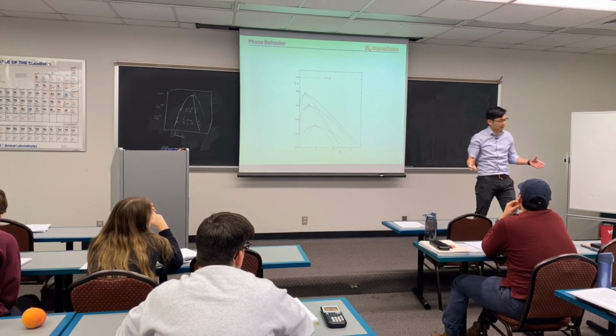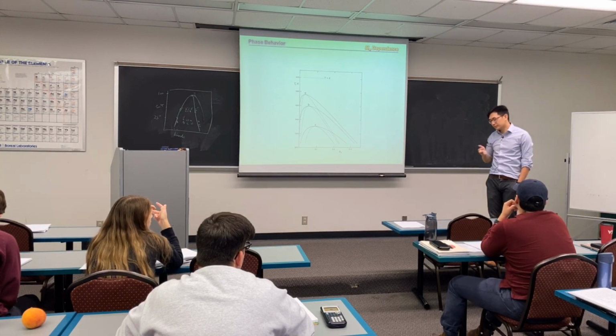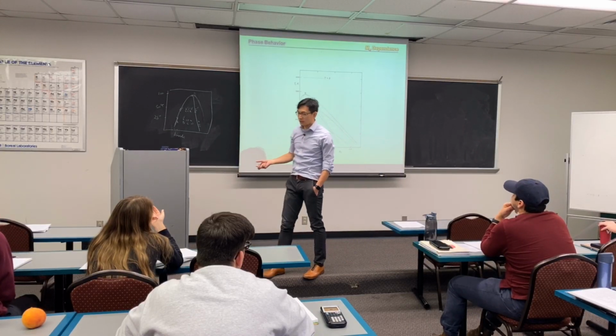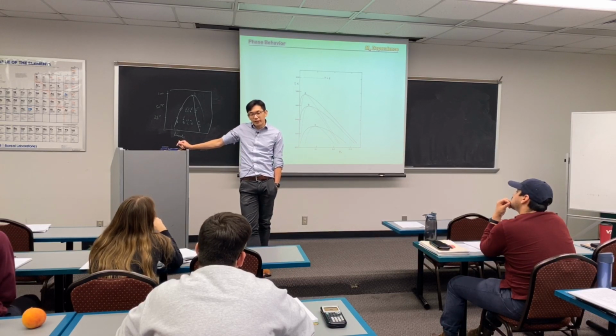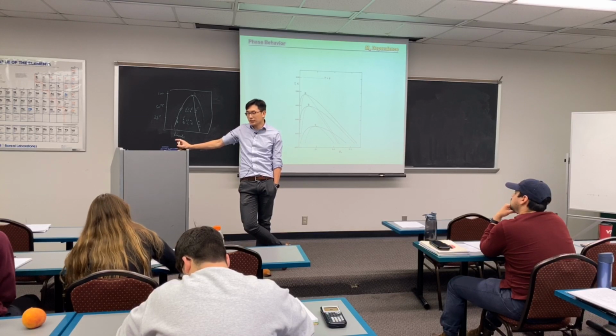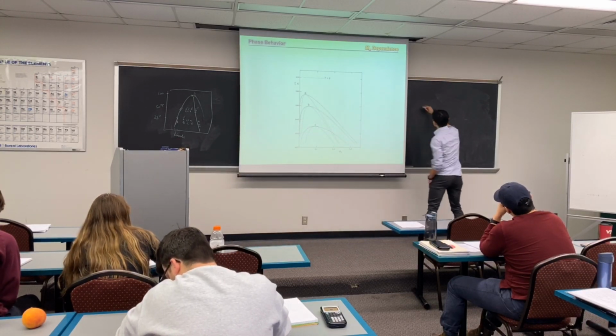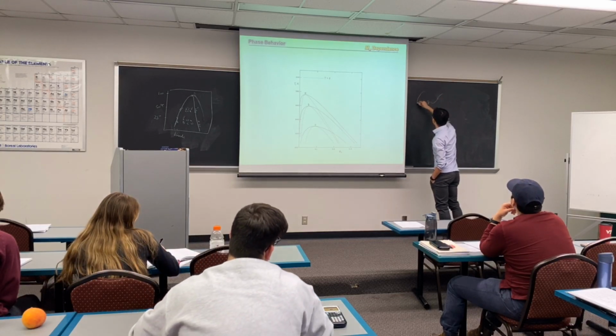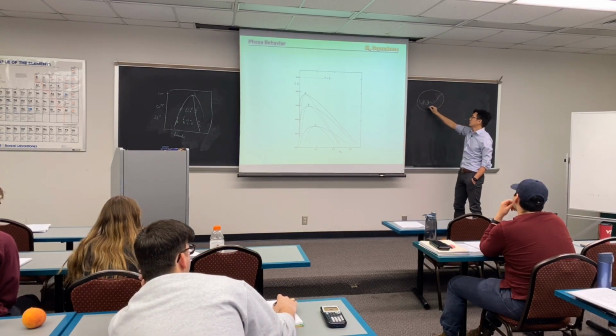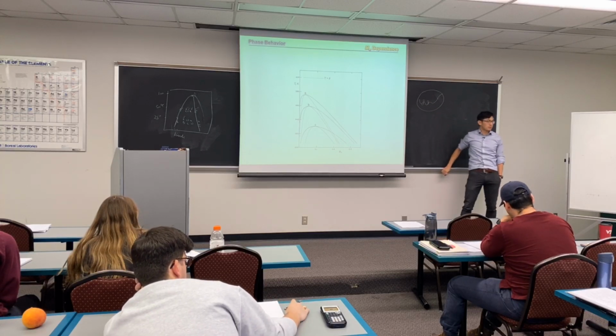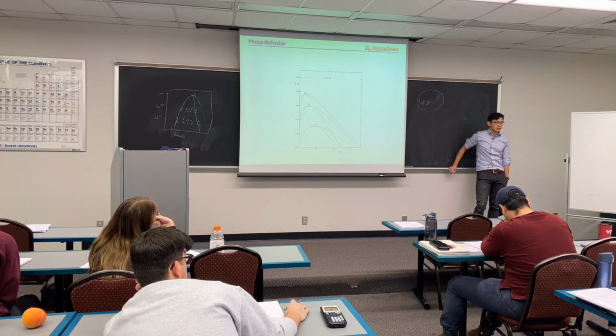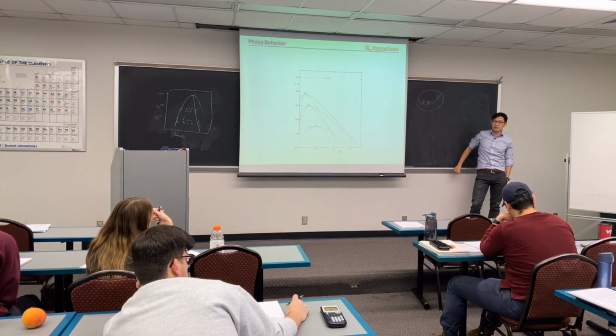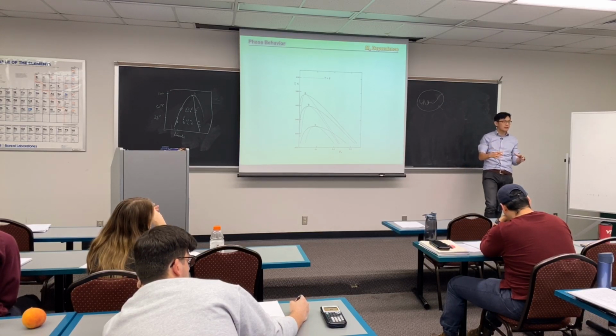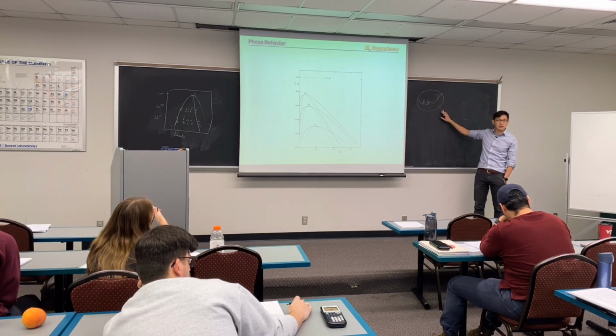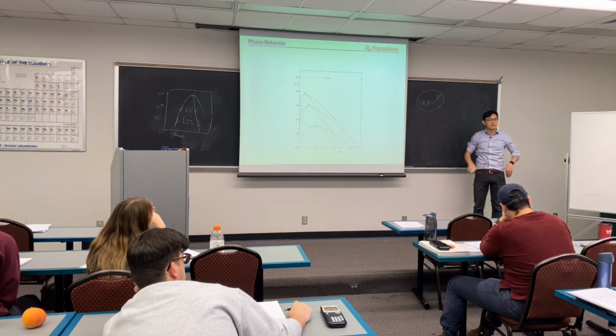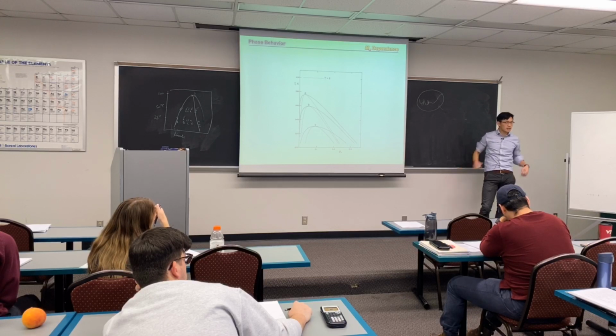So what causes the molecule to expand? The interaction with itself, so it will have a self-repulsive force, right? You can also consider it as osmotic pressure inside the individual polymer chain. If you consider one chain coming from one large sphere, inside this sphere you have polymer chains. You can consider what would be the osmotic pressure inside this particular globule. The osmotic pressure will drive the solvent into this globule because you have polymer chain inside, and outside you have pure solvent. So chemical potential will drive your solvent into this particular imaginary sphere. You would cause the chain to expand.